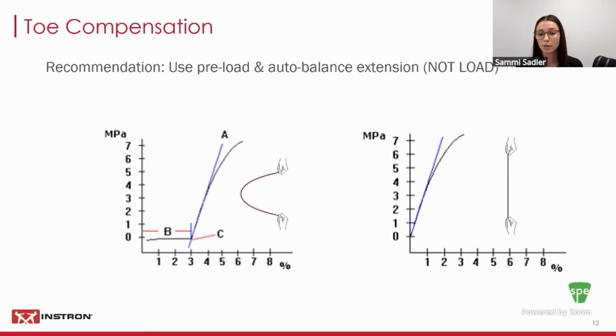It's also extremely important to note that all the loads that we're seeing during this process are real and true, and it's advised to not auto balance our load at this point. And it's recommended that a preload and auto balance of strain is used to remove the toe region, which is required by both ISO and ASTM standards at the beginning of each test.